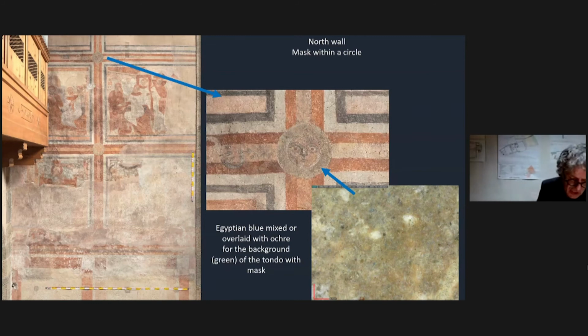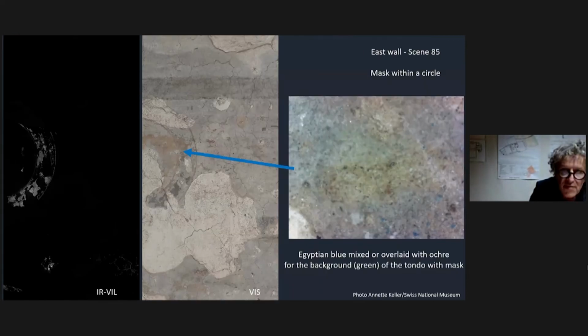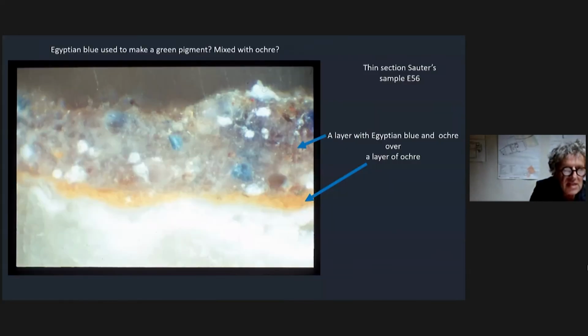Other cases show a use of Egyptian blue in connection with the creation of a green tone. In particular, it appears mixed or overlaid with ochre for the green background of the tondo with mask. This is also confirmed by the thin section of a sample.